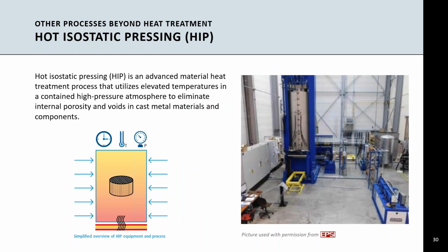That brings us to hot isostatic pressing. This is a process in which temperatures are raised up to as high as 2,000 degrees Celsius and pressures up to 2,000 bar. The reason for this is to eliminate internal porosity or voids that take place either from a casting process or an additive manufacturing process.